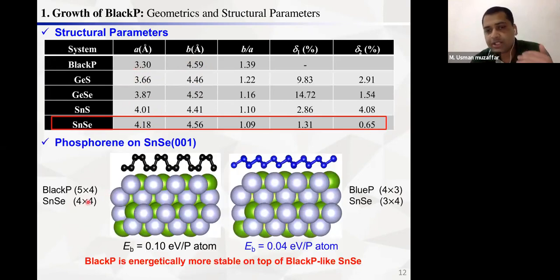If we consider black phosphorene as a 5x4 supercell of black P and a 4x4 of SnSe, I'm trying to compensate this number with this one. If we multiply this one by 5 and this one by 4, then it matches well. You can see the lattice mismatch along the A axis is just 1.31%, and along the B axis it is also very small, 0 point something. So this small lattice mismatch can be easily adjusted in experiments.